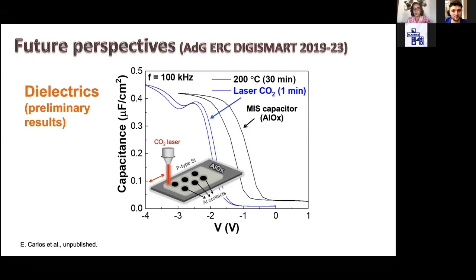For example, this was an example of a capacitor based on aluminum oxide. The black line was done at 200 degrees during 30 minutes. And the blue one is for the same capacitor, but it was processed by a CO2 laser with infrared radiation during, for example, 1 minute, but simultaneously we pattern the devices, the layers.